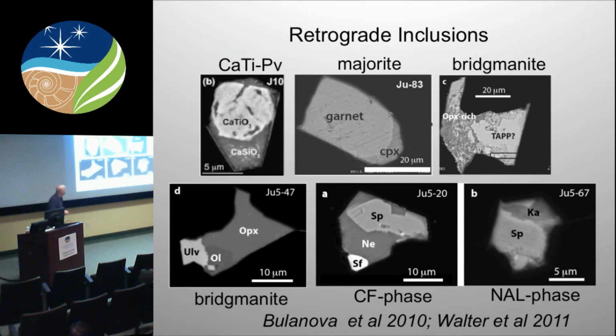When I started doing this about 10 years ago, I took pictures, made a photocopy, cut them out with scissors, and weighed them. And that actually works pretty well, because now we've used synchrotron tomography, and we've looked at the whole inclusion before it's exposed, and can reconstruct it that way, and we get roughly the same answers. One costs about 30 cents, the other costs about, I don't know, $30 million.